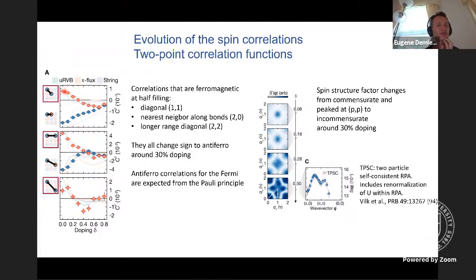At half filling, they're ferromagnetically correlated, but as we increase doping, it changes to antiferromagnetic correlations. We take two other sites, in this case next nearest neighbor, but all in the horizontal direction. Again, this is ferromagnetic at half filling, but as we dope this system, the sign of correlation changes from ferromagnetic to antiferromagnetic. We take an even longer range correlation, one that would be ferromagnetic at half filling, and again it changes sign, and they all change sign at approximately the same doping of around 30%.